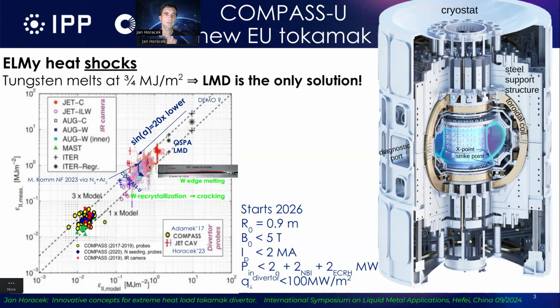And based on this simple scaling, we can predict the values for ITER of about 15 megajoule per square meter, which you decrease by a factor of 20 thanks to magnetic field inclination, which means that you get to a value of about 1 megajoule per square meter. This means that the whole divertor would melt every millisecond, so 10 times or 100 times per second. During 1 millisecond, it would be melted and resolidified, and it will change the shape of the divertor if we don't do anything significant about it.